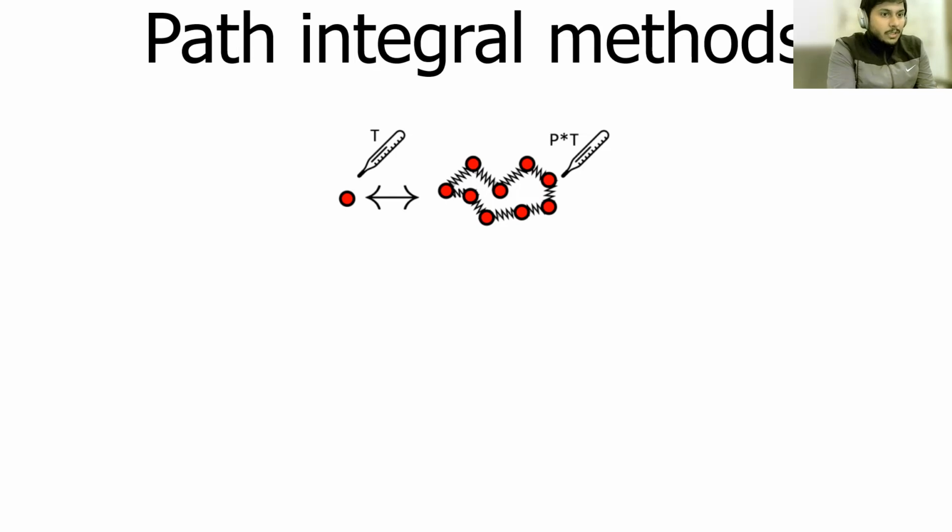What you say is that, well, if I displace my nuclei on a time scale of a femtosecond, my electrons would have already relaxed, let's say, at an attosecond time scale. So there is no point including the coupling between their dynamics. So you just say, well, I move my nuclei, my electrons have already relaxed. Let's just compute the expectation value of the energy and use that to drive my dynamics.